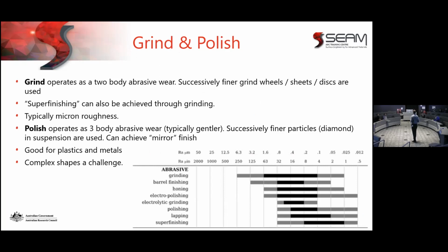And good old grind and polish. So any metallurgist will tell you to get a nice metallographic sample, you grind it and you polish it. Options for your grinding is a two-body wear process, a little bit harsher, and gives you micron style roughness. Go on to a polish, which is a three-body abrasive process, a little bit more gentle, going in successive finer polishes to your mirror finish. Good for both metals and plastics, complex shapes are doable. So these glasses were made with grinding and polishing. So if you're wearing glasses, most likely the back surface has been ground and polished. And there goes my solder.